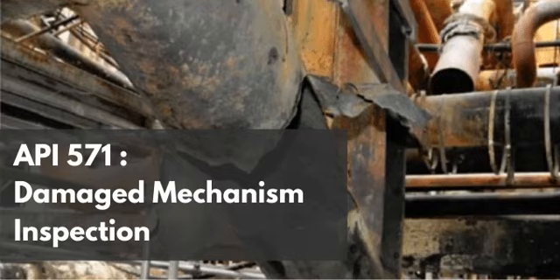Exactly. So if an inspector or a pipe fitter takes a heavy, rigid grinding wheel or an overly aggressive, abrasive flap disc to the weld, just trying to clean off the external paint, rust, and scale, they are not just cleaning the metal, they are generating intense, localized heat and lateral friction. They're essentially plastically deforming the surface layer of the steel. Yes. The abrasive source literally shears the ductile ferrite phase right over the top of the tight crack opening. It acts like a metallurgical caulking compound. Oh, wow. It completely bridges the gap at the surface. The crack is entirely intact and still propagating underneath, but the surface is mechanically sealed.